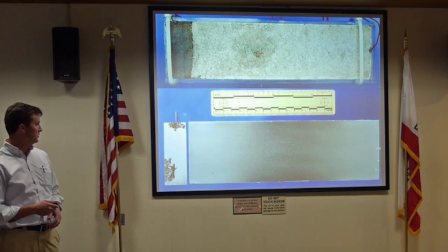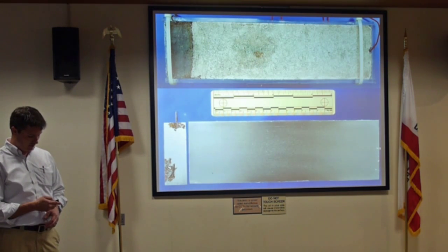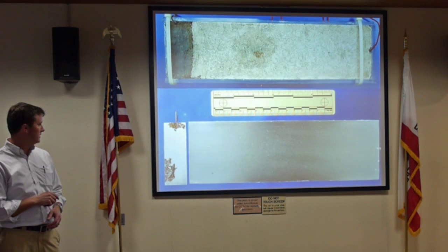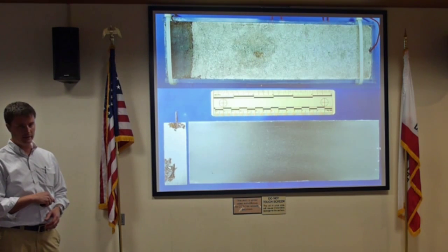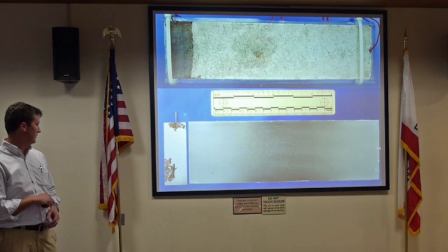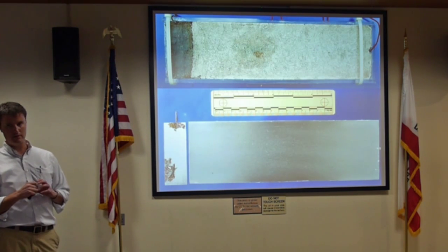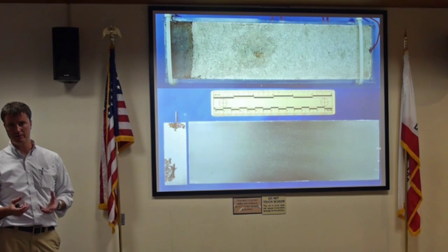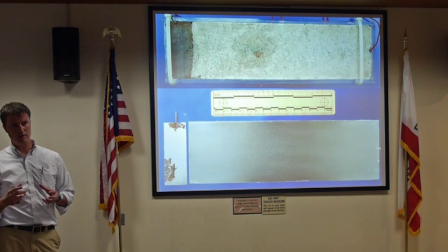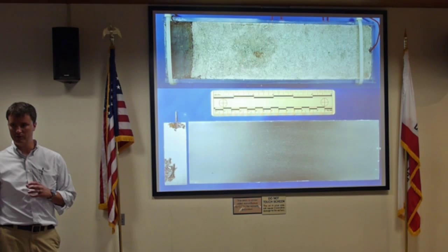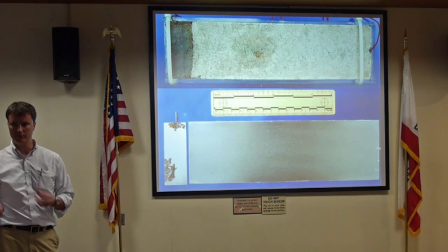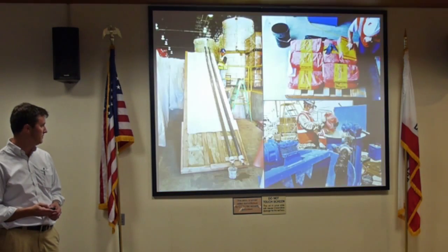just looked at the current between the two, and then ultimately, after letting it run for several weeks, also saw that yes, in fact, we were able to drive corrosion, seeing the corrosion product forming here just by having essentially two different grouts of one. So basically, this grout segregation on its own, no additional outside materials or chloride, seawater, whatever, was able to drive this corrosion process.